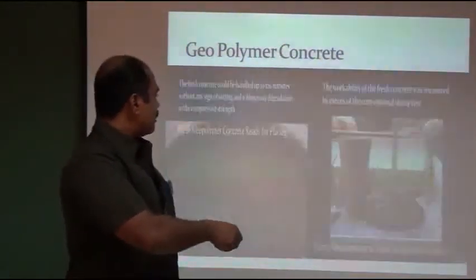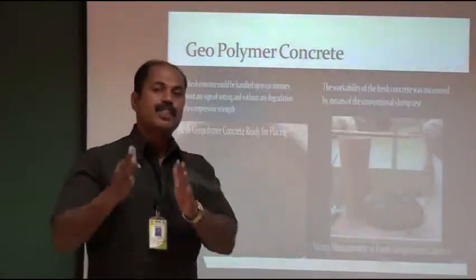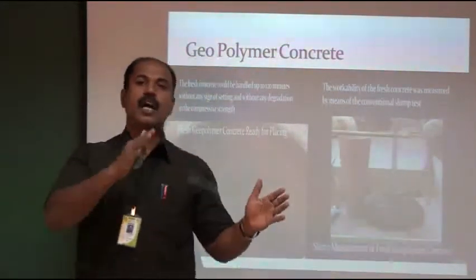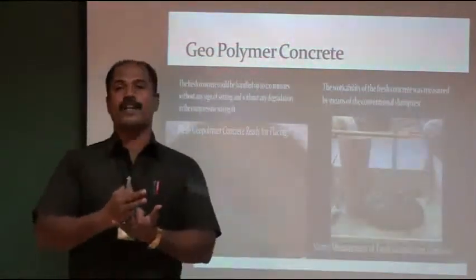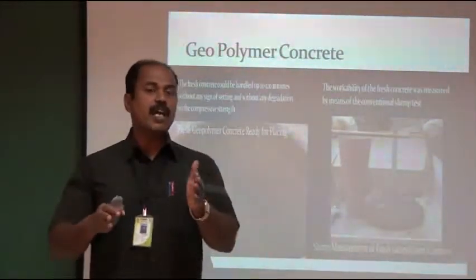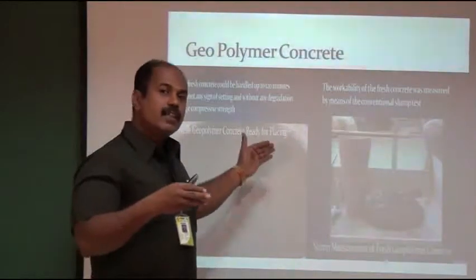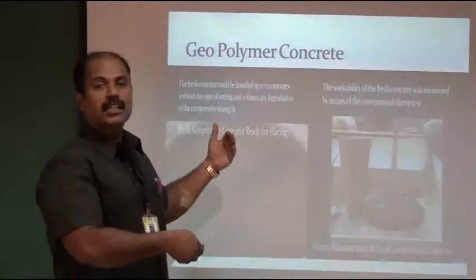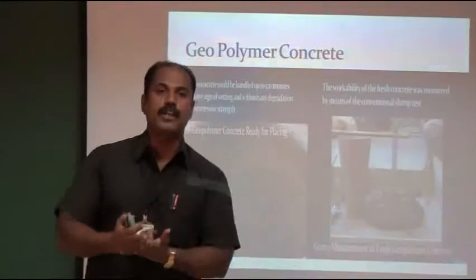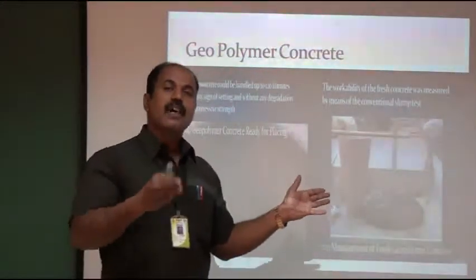You check the slump, which is very good compared to conventional concrete, and then this is the making of the concrete. What is the advantage of geopolymer over conventional concrete? Before we discuss the difference between conventional and special concrete: geopolymer concrete is high strength concrete. We can achieve 110 MPa in 28 days. It is possible. But in conventional concrete, as per the mix design, we reach 40 MPa or 50 MPa. But this is very high strength concrete and its durability properties are much higher than conventional. What is the main disadvantage of geopolymer compared to conventional concrete? The cost of the concrete. The availability of chemicals is higher than conventional concrete. That's the main disadvantage of geopolymer.